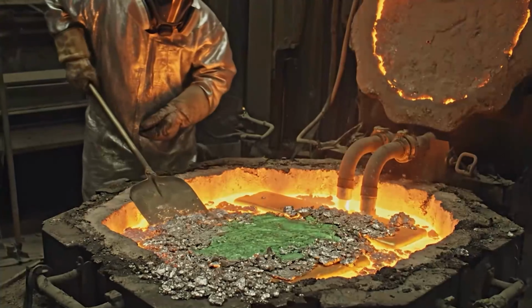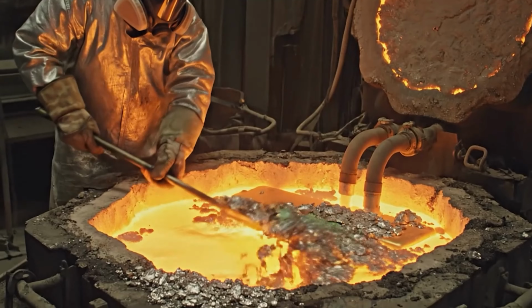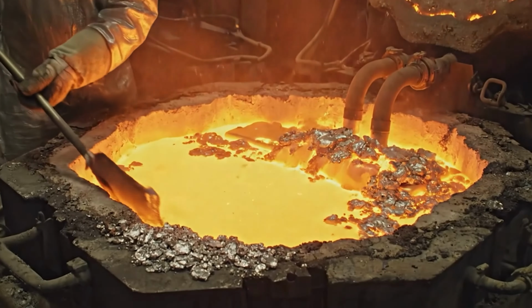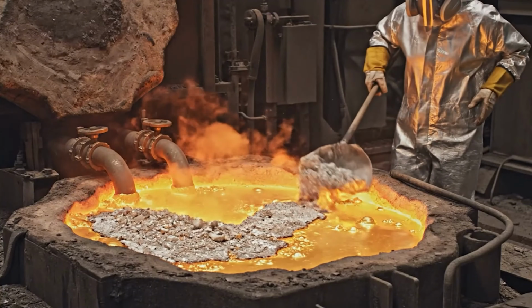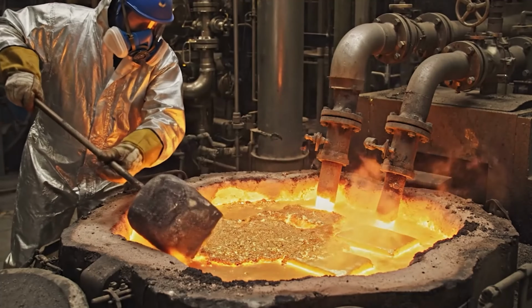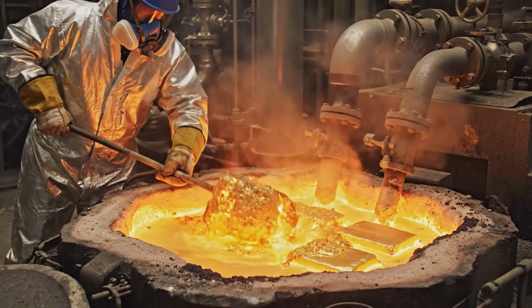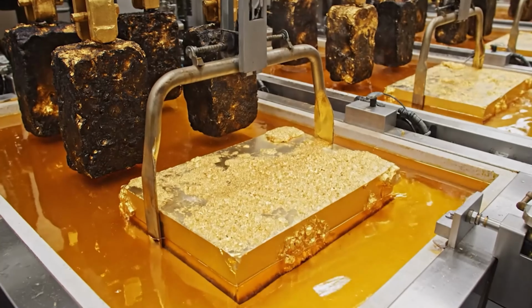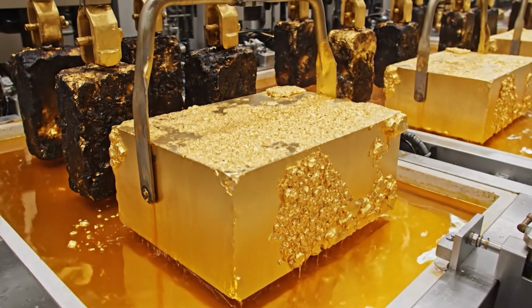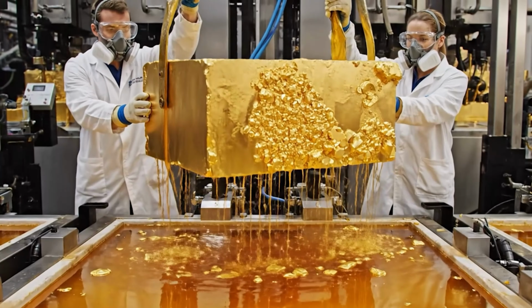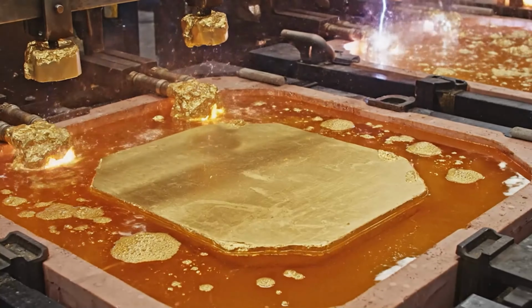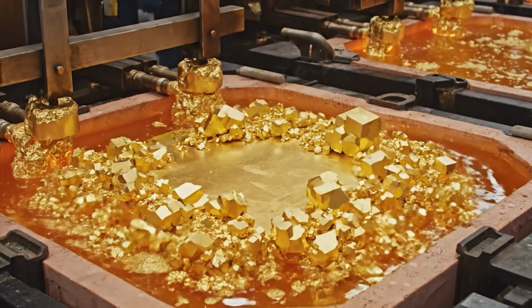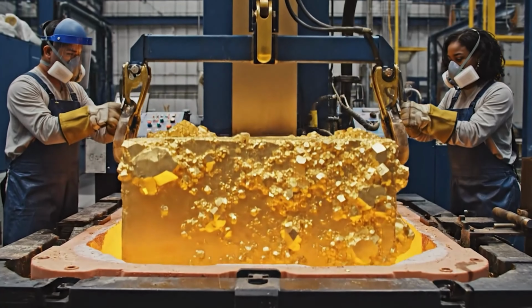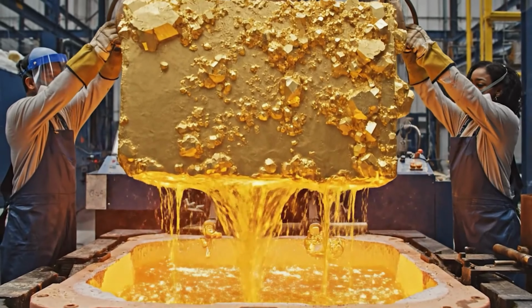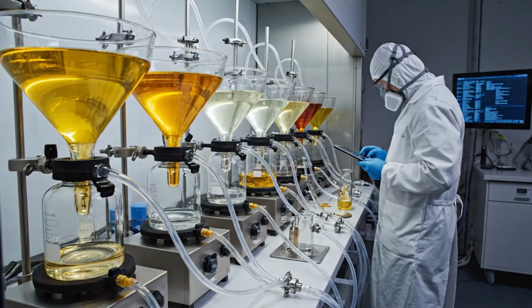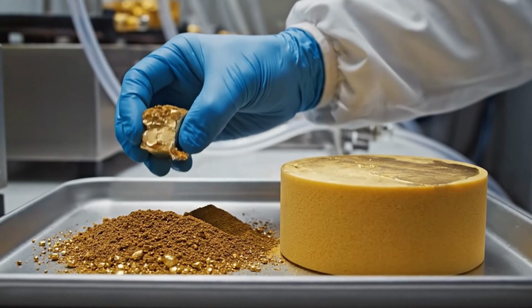At specialized refineries, the Miller process, most common, bubbles chlorine gas through molten doré, removing silver and base metals as chlorides, yielding 99.5 to 99.8% gold. The Wohlwill electrolytic process gives ultra purity. Gold anode dissolves in hydrochloric acid with gold chloride electrolyte. Pure gold plates onto a cathode, achieving 99.99%, or four nines, purity. Some refineries use aqua regia or other solvent extraction methods.